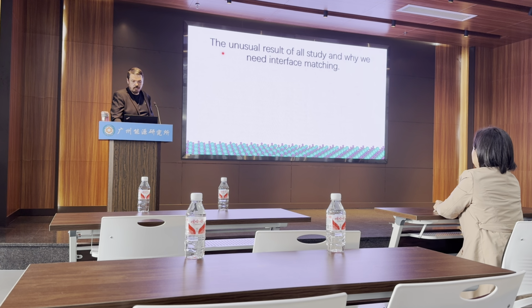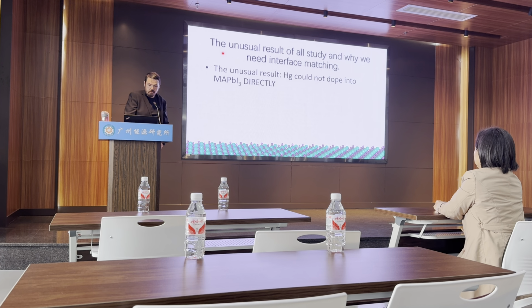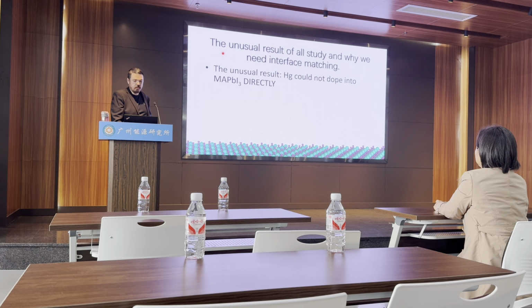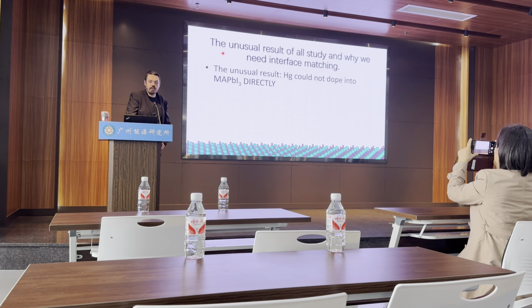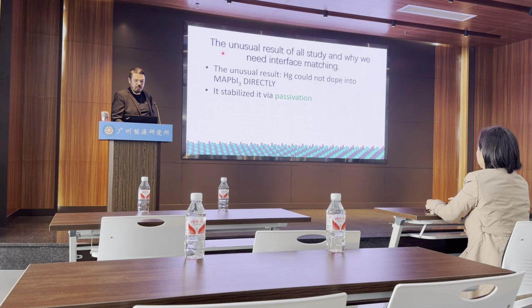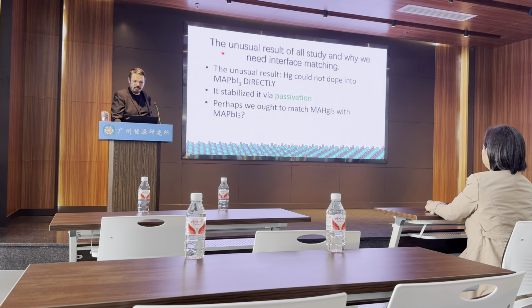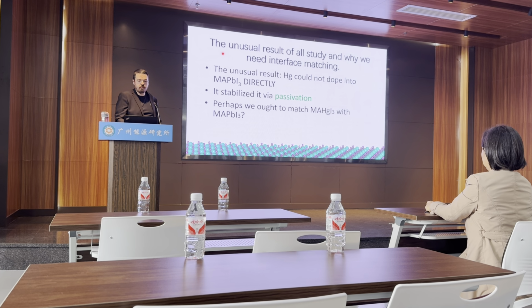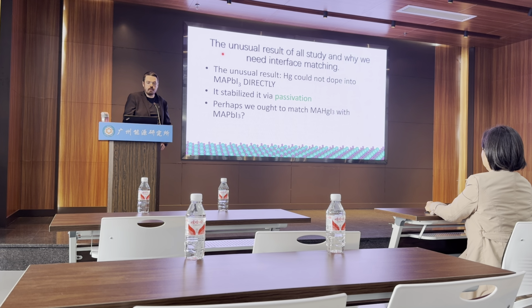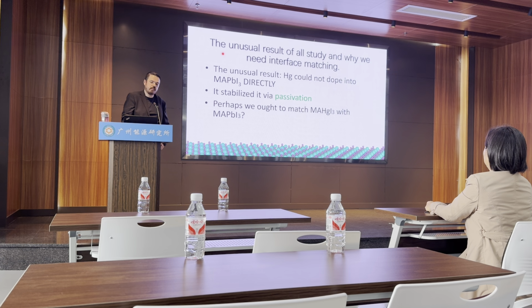The main result is that mercury does not dope into the MAPI directly, but it stabilizes the MAPI the most. So it stabilizes via passivation. So what is the passivator? First of all, we thought maybe the passivator is something that's perovskite-like, so MAHgI3, for example. So maybe it matches on with the perovskite. This was the idea that Marina came up with, and I had to check it.